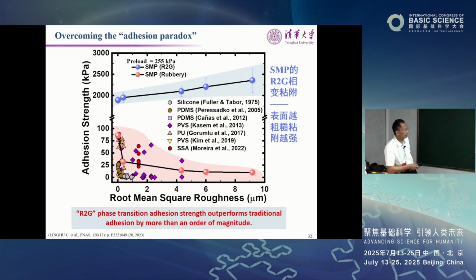Okay, now we measure adhesion strengths as a function of surface roughness. You see, these are all traditional, existing technologies. They all suffer from the adhesion paradox. The higher the surface roughness, the lower the adhesion strength, with the exception of our phase transition adhesion. In the case of phase transition adhesion, first of all, as surface roughness increases, the adhesion actually does not decrease, it increases, because the interface becomes longer. We have the rougher the better.